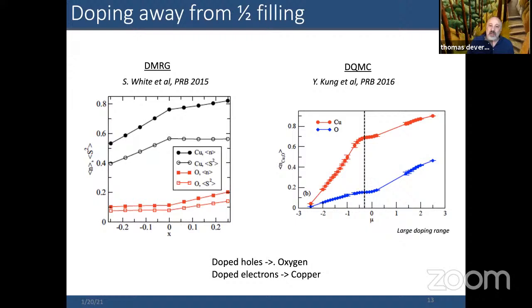So then if we dope away from half filling for three-band DMRG and three-band quantum Monte Carlo, we have the results that we would expect. These are plots of hole doping, and for DMRG, the expectation value of the spin. When holes are doped in, they go predominantly on oxygen, or a little go on copper, creating some d8s. And if we dope with electrons, they go mostly on copper, creating d10s. And of course, this is determined largely by the parameters that I showed in the previous slide.